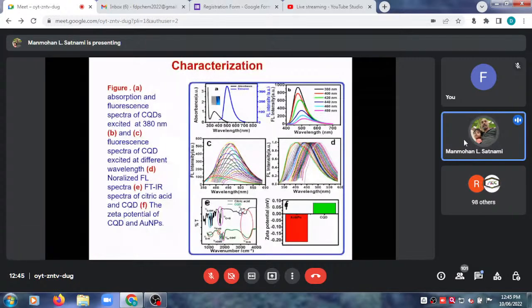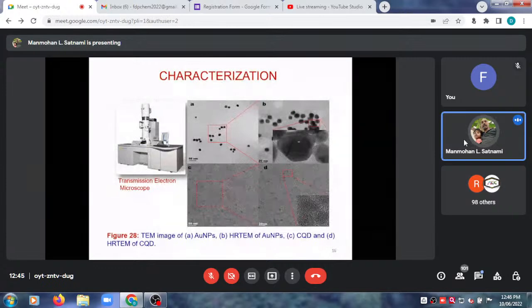Here is the zeta potential measurement we performed for the carbon quantum dot and gold nanoparticle. You can see the zeta potential value for carbon quantum dot is positive, and zeta potential of gold nanoparticle is negative, and therefore the negative and positive can have a very good electrostatic interaction between gold nanoparticle and carbon quantum dot, so that both can come closer to have the effective FRET process between them. Of course, this is gold nanoparticle characterized through TEM image.